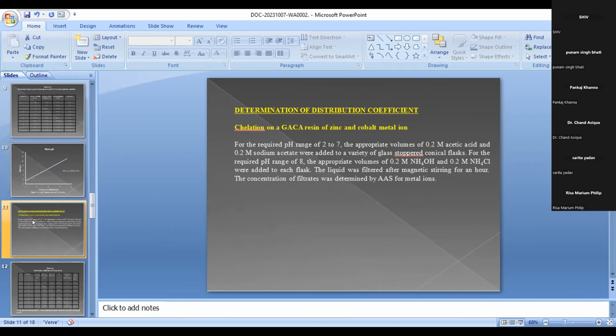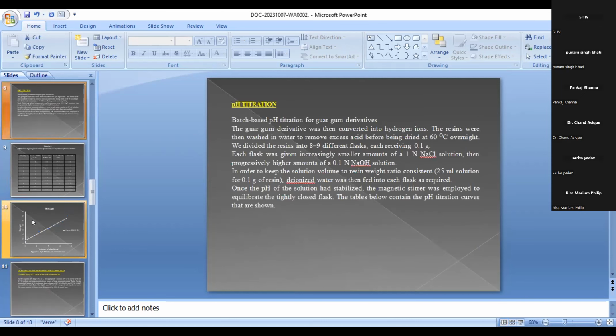Sir, pH titration is the base method. pH titration for the guar gum derivatives. The guar gum derivatives were converted into hydrogen ions. The resins were then washed in water to remove the excess acid before being dried at 60 degrees overnight. We divided the resin into 8 to 9 different flasks, each receiving 0.1 gram. Each flask was given decreasing amounts of 1 normal NaCl solution, then progressively higher amounts of 0.1 N NaOH solution, in order to keep the solution volume to resin weight ratio constant, and deionized water was added to each flask as required.